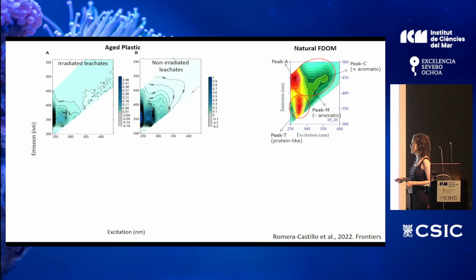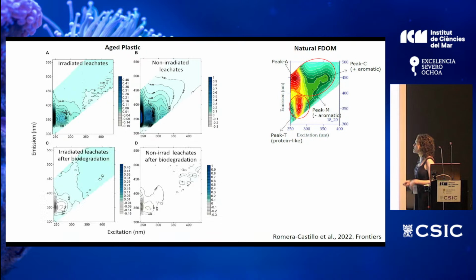Probably these are polyaromatic hydrocarbons. And notice also the difference of the scale. So here the fluorescence intensity is higher. And this could be because the one that is exposed to radiation has photodegraded the fluorescent substance here. So it could be the same amount of fluorescent matter, but this has been photodegraded, so that's why we have less signal here. And then we saw if those fluorescent materials released by plastic were bioavailable for microbial uptake in the second part of the experiment.